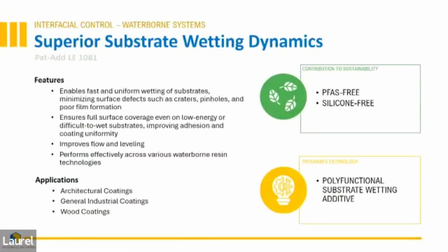All right, we need wetting agents in order to get the continuous part of the coating onto the substrate. And I'm going to be discussing now these PFAS-free. That seems to be a big item of interest for paint manufacturers because PFAS is now a scrutinized material because of its fluorine-carbon connection that is so resistant to degradation. And we used it for that property, but now it's come back to haunt us because these are now known as forever chemicals. And so much of the effort of the industry to achieve higher degrees of sustainability is to replace those PFAS materials with what is now called PFAS-free.